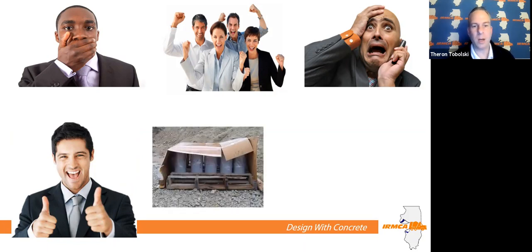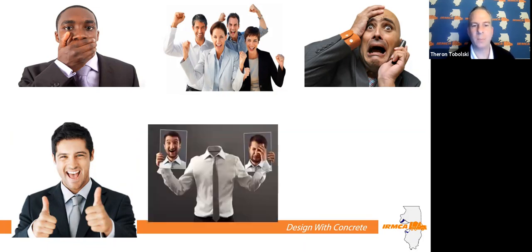Here we see a good attempt, right? We've got cylinders, we've got plastic bags over them, they've got some cardboard over them. They've taken some extra time and care. Is this right? Kind of yes and no. They've covered the cylinders with some plastic and got some cardboard to keep the sun out, but unless it's going to be 60 to 80 degrees for the 2 days that they're out on site, they need to put them in a curing box to make sure they're the right temperature.